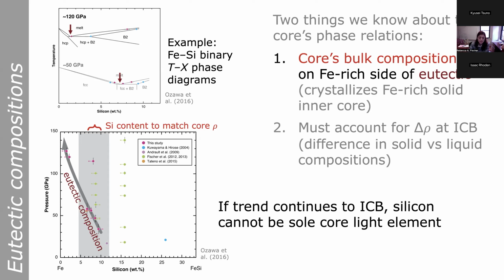So if this trend continues to inner core boundary conditions, what this means is that silicon can't be the sole light element in the Earth's core, because the core's composition would be on the wrong side of the eutectic in the iron silicon binary. Note, it's hard to extrapolate these things because you can have subsolidus phase changes that can suddenly change the eutectic composition. It's very, very hard to do these experiments at 330 GPa. So extrapolation is often necessary. But that does make everything I'm about to say something you should take with a grain of salt, because we really need more high pressure data on this.